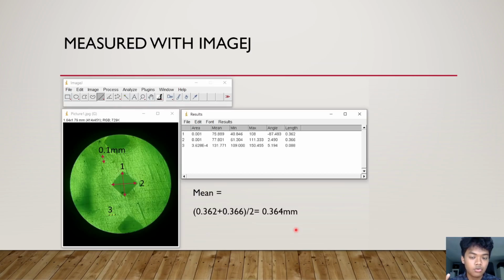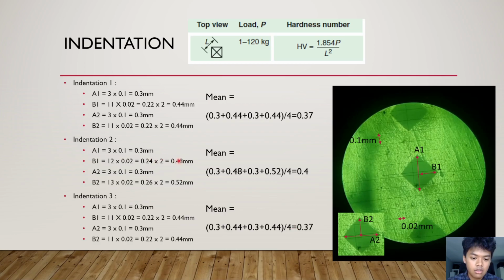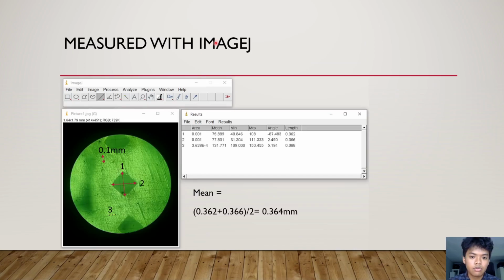Okay, let's talk about indentation number 2. Indentation number 2 has the most different data measurement than the other 2. So what I did was I input indentation number 2 into ImageJ, and I measured with this, setting this as scale. I measured 1, 2, and then 3, and what I got was, for its diagonal number 1, 0.362, quite similar to what we got for indentation number 1 and 3. And for diagonal number 2, I got 0.366. Also not that far, maybe because I made some error here, since I have to sort of eyeball it.